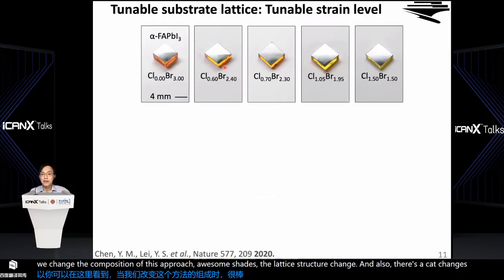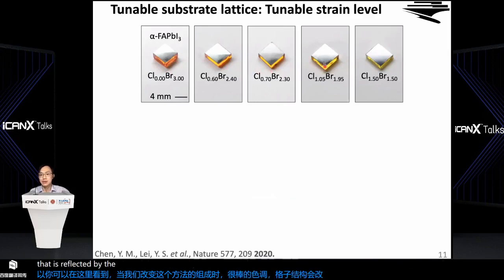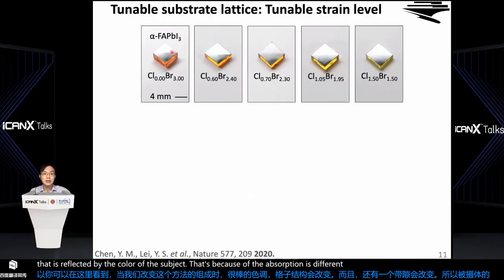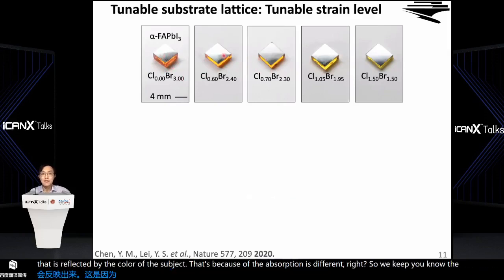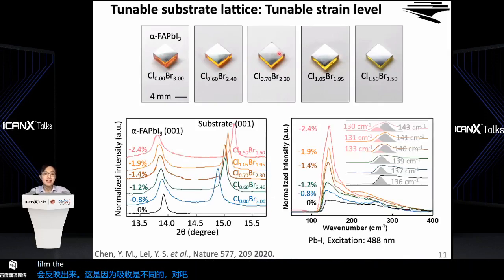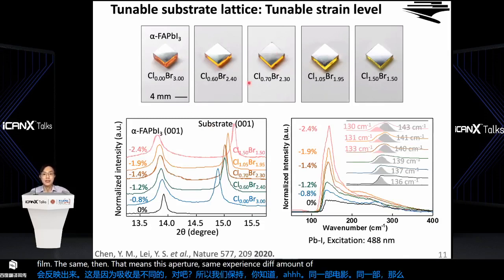That is reflected by the color of the substrate. That's because the absorption is different, right? So we keep the epitaxial thin film the same. Then that means this epitaxial thin film will experience a different amount of strain on top of these substrates.